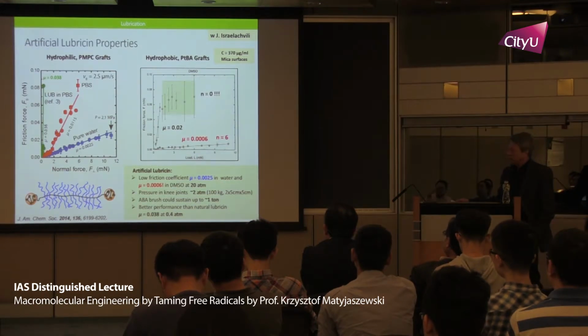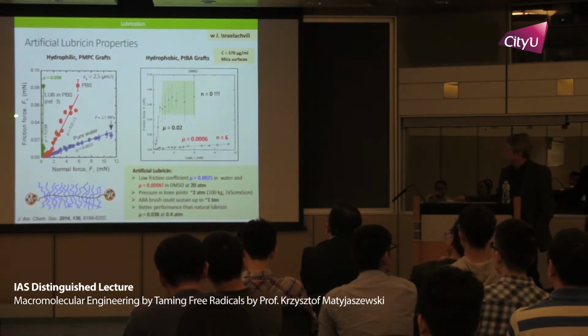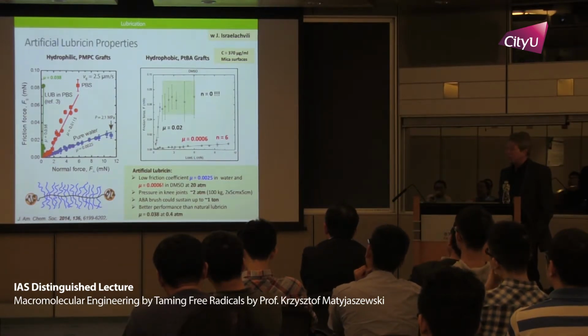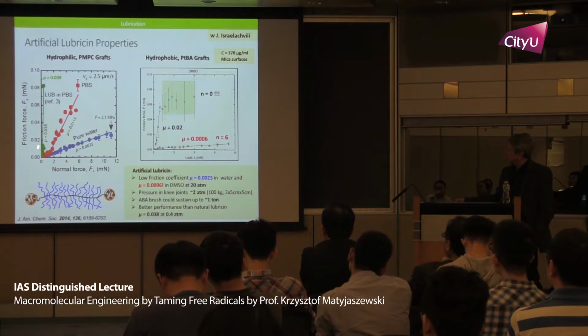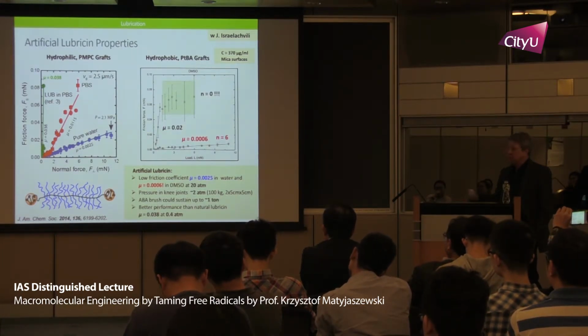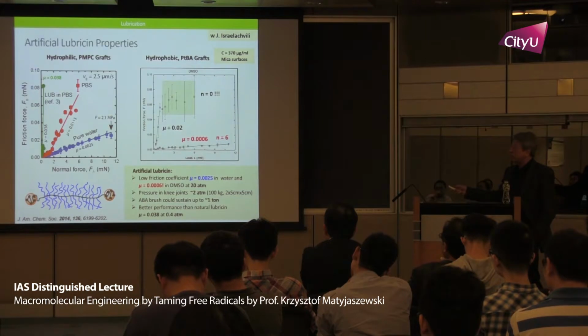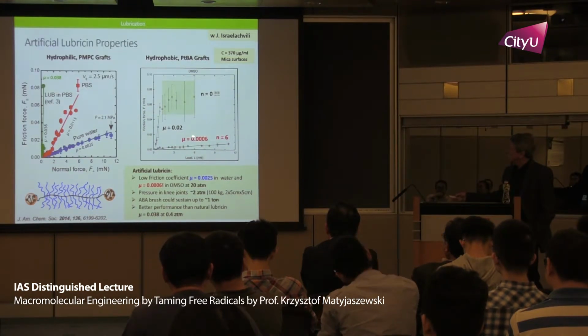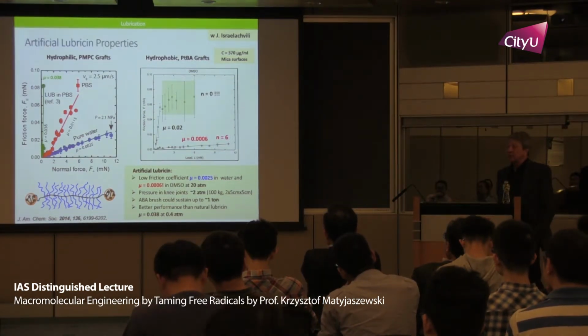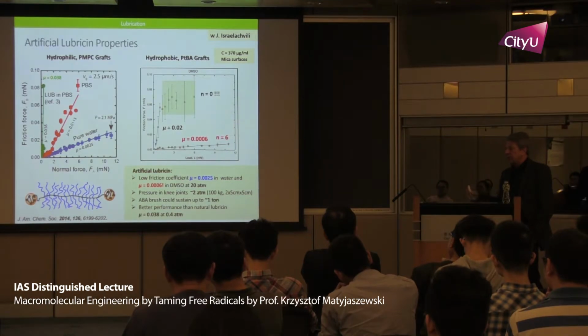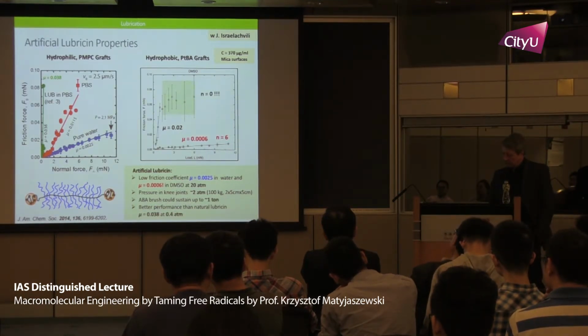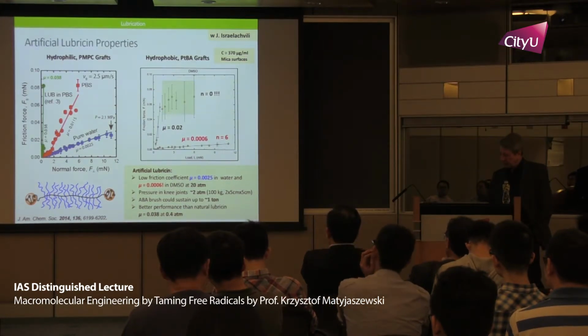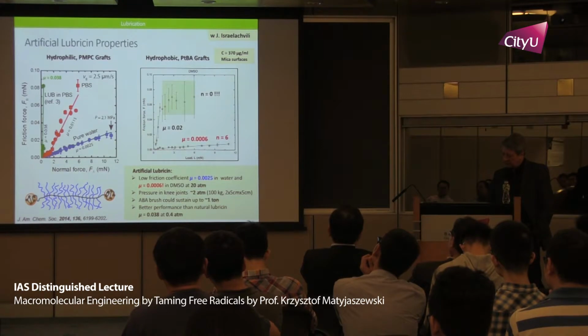So here is really how you compare this natural lubricant with synthetic ones. If you have a larger slope, you have a larger friction. Here, you have a friction coefficient by a factor of 10 or even more lower. And this natural lubricant, at applied higher pressure, this normal force, just breaks. And this can survive to much larger values. If you take even this hydrophobic system, this is done in DMSO as a solvent, you could see that this friction coefficient is like about a factor of maybe 100 times lower. So they are practically frictionless materials. So this may have some applications in joints, essentially, after both hip and any kind of arthroplasty.